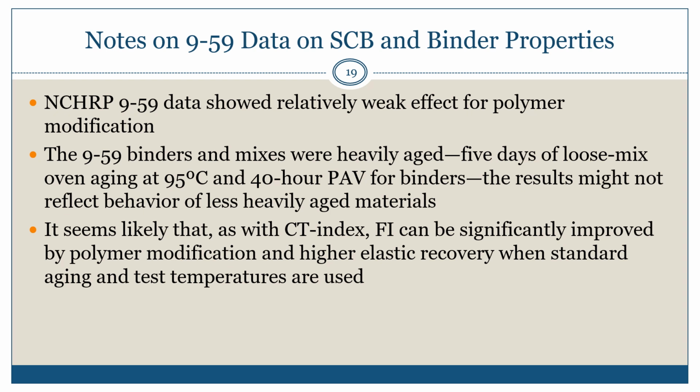Again, 5 days of loose mix aging for the mixture and a 40-hour PAV for the binders. This seems to attenuate the effect of polymer modification. And the fact is, we think that if we would have done this or similar research using less heavily aged binders and mixtures, we would have seen a greater effect for those polymer modified binders.